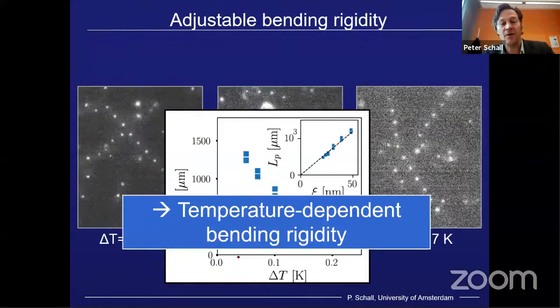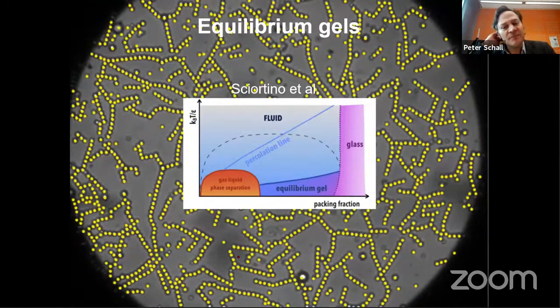Okay. Now, next we were adding a few 4-patch particles. So what happens if you do that? You have chains. Now you're adding 4-patch particles. You're introducing branching points. In fact, what we see is that we get an analog of a cross-linked polymer, which means now the polymers can bind to each other via these higher valency particles, and they form a space-spanning network, which we could image and analyze in detail.